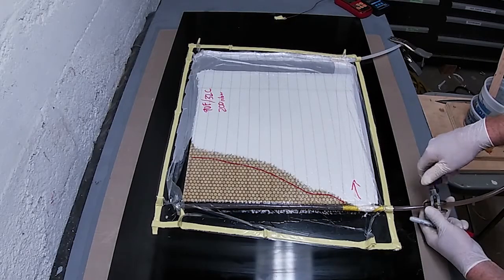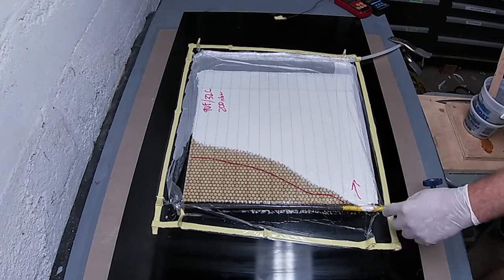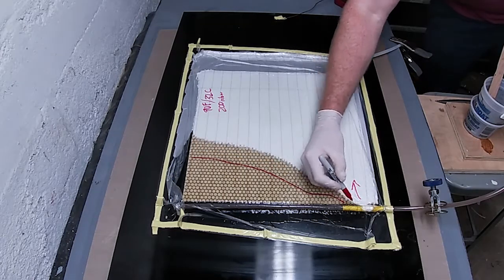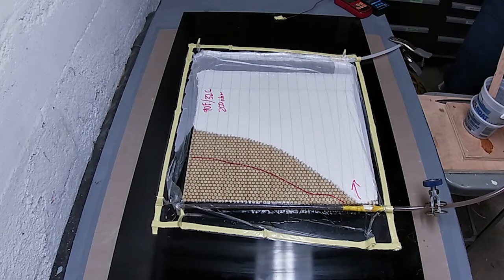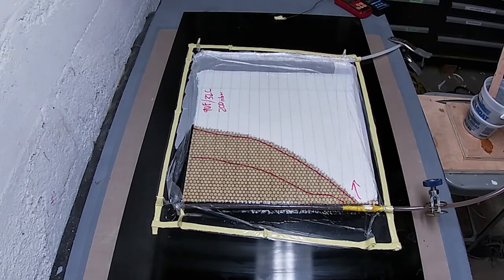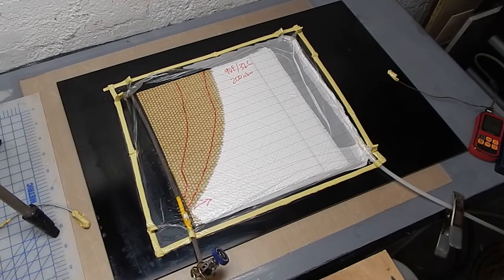And already we can see here one issue I'm having because of that tape that I wrapped around and because I had to slide that feed line in. I'm getting resin only feeding from one side and it's kind of choked off on the side closest to me here.